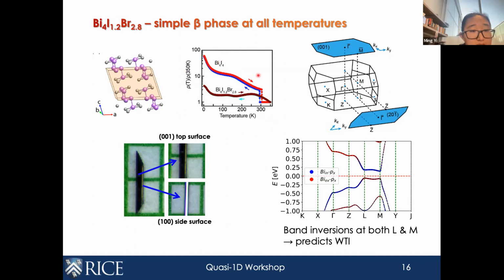So in bismuth iodine, you see this first order transition that separates the beta phase and the alpha phase. In this 2.8 amount of bismuth bromine, there's no transition, and they have also confirmed this with single crystal XRD to show that this is really a stable beta phase down to low temperature. And from first principle DFT calculations, we do see that there are two band inversions at both the L point and M point. That's the state that we expect a WTI for this stable beta phase.